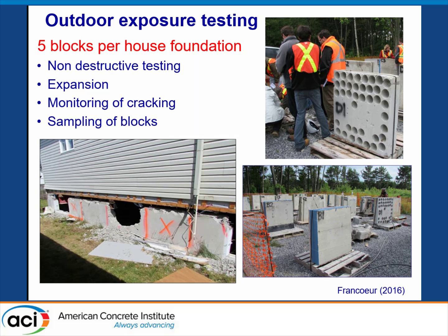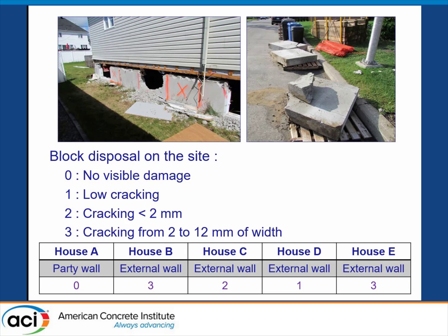We also work with the concrete blocks from the houses, and we put the blocks in an outdoor exposure site to measure the expansion, monitor the cracking, and sample the blocks. I will just show you a few examples. We selected different houses according to the damage at the moment of the demolition.